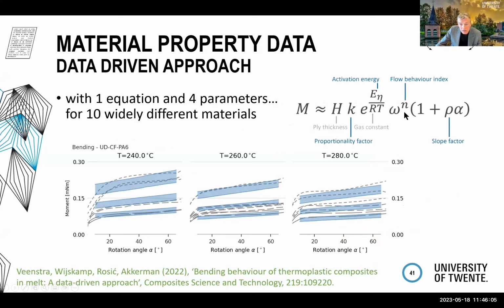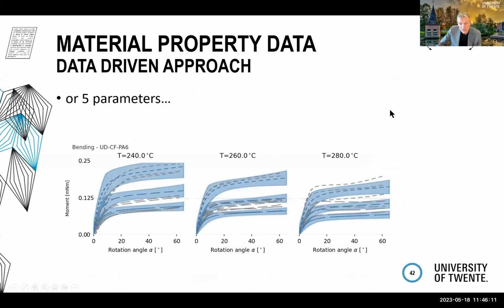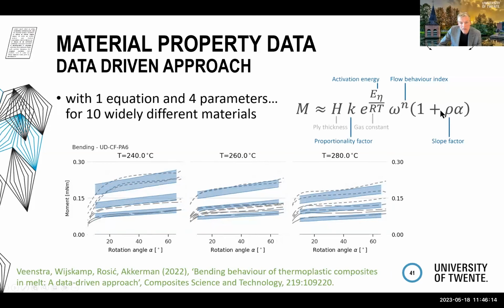describing the deformation behavior, describing the effect of the slope. Okay, so this is the slope, this is the rate, this is the temperature, and then there's one further parameter, a proportionality factor. Well, it's like an E modulus for elastic systems, which characterizes the materials. We think we get a decent fit for all these 10 materials. So to our idea, this would be a reasonable description of the actual bending behavior.